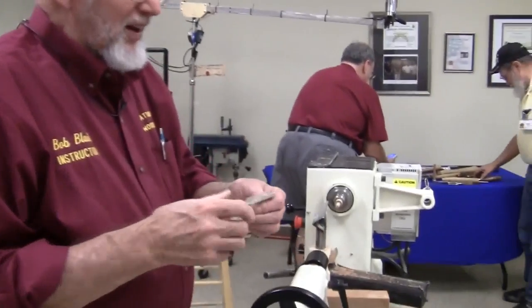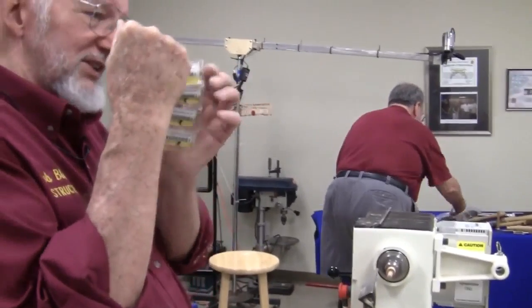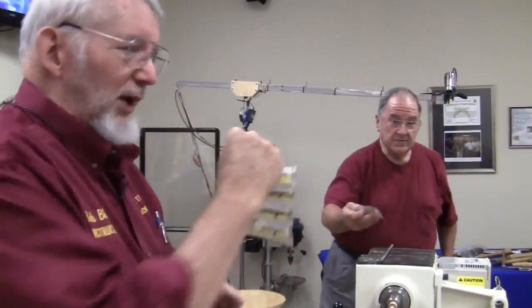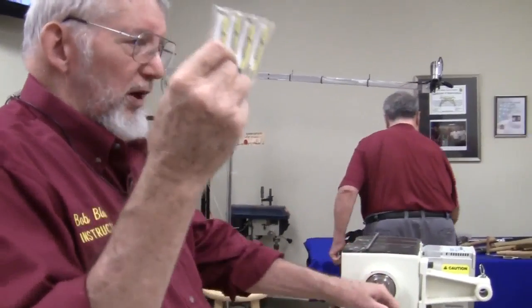those little tool bits. That goes into a heavy bar on a metal lathe carrier. There's just a little bit of that sticking out, and it cuts metal. That will run at red heat and hold its edge pretty well. It does not get soft at 1400 degrees. It's still got the strength. So you could run that in a metal lathe at red heat, again about 1400 Fahrenheit, and it would hold up. Which means before that, they didn't have tool steel that would stand up to that, so you had to take lighter cuts.